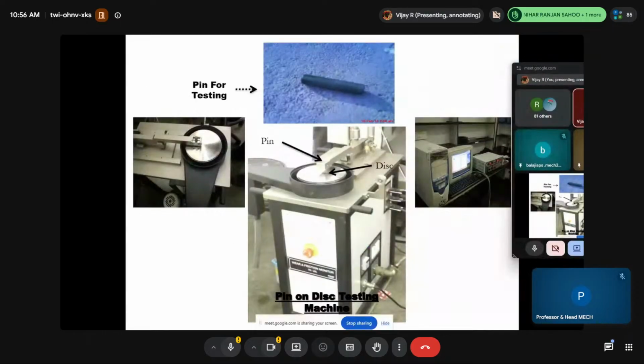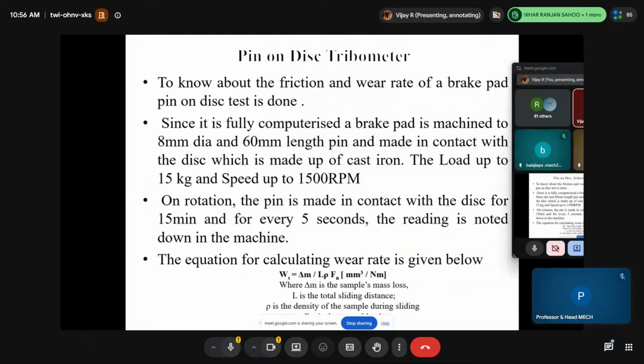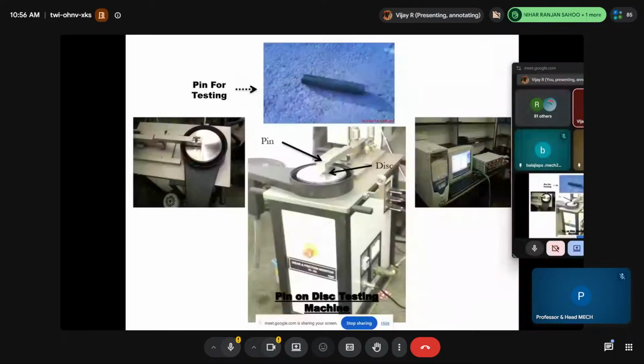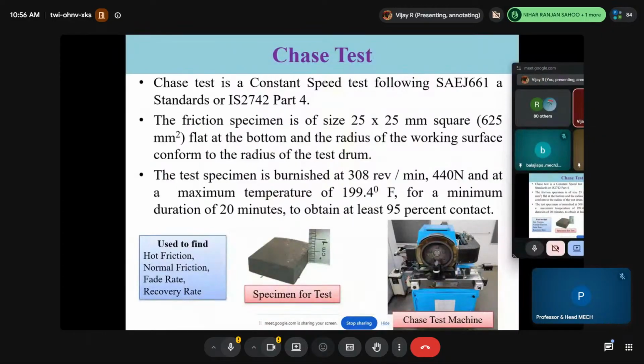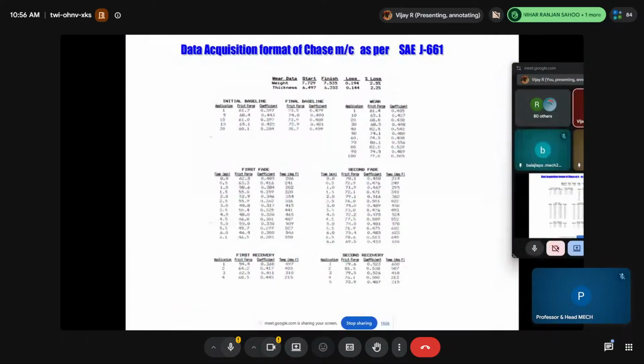So the pin-on-disk is shown here. This pin-on-disk will have the pin for testing. The disk will rotate at a certain RPM, the pin will be placed, and the digital interface is given. Then the Chase test, where the sample is cut into 25 by 25 and placed in the holder. It will be like a drum, the braking conditions will be applied, and similarly you will get an idea. This is the Chase test result.